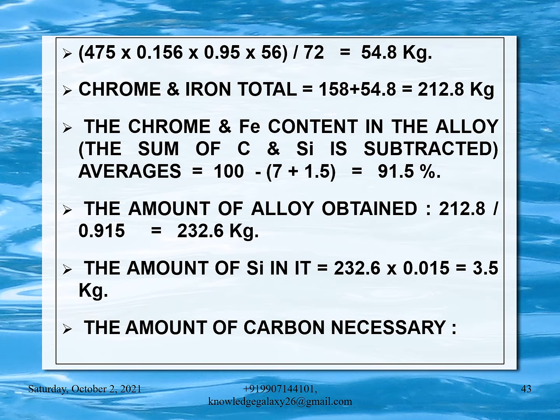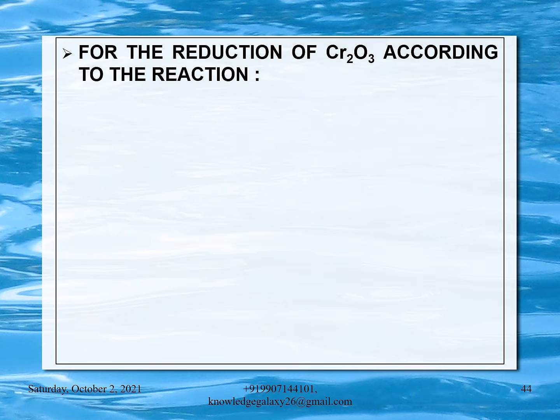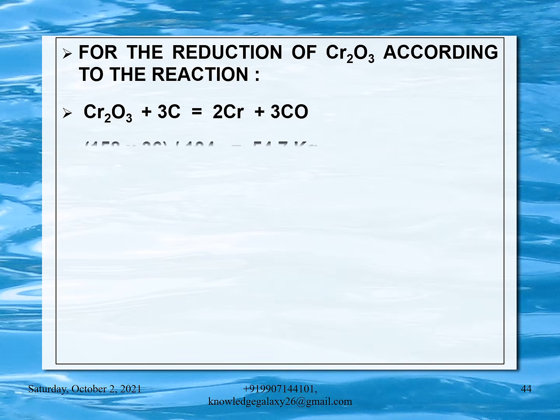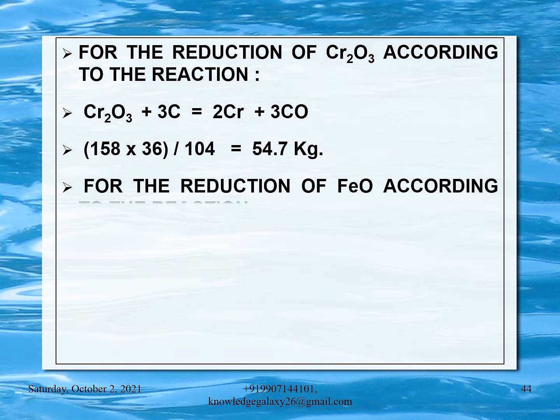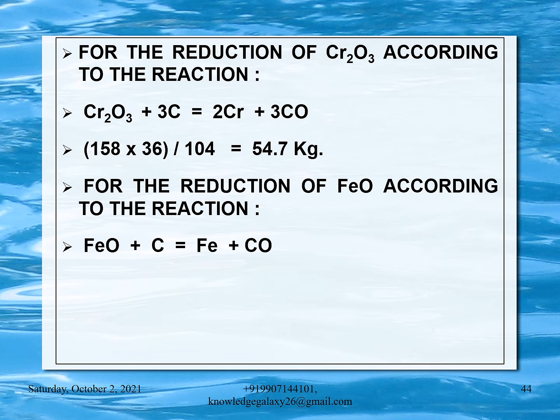The amount of carbon necessary, let us calculate. For the reduction of Cr2O3 according to the reaction Cr2O3 plus 3C is equal to 2Cr plus 3CO, it comes to 158 into 36 divided by 104 is equal to 54.7 kg. 158 is the alloy content of Cr2O3. For the reduction of FeO according to the reaction FeO plus C is equal to Fe plus CO, it comes to 54.8 into 12 divided by 56 is equal to 11.7 kg.